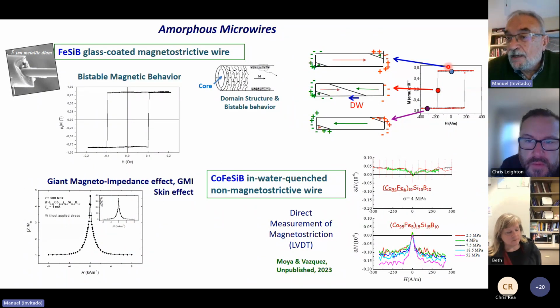So we are in a positive remanence where we have a single large magnetic domain, but at the very end where we have some magnetic charges. Then we applied a field in the opposite direction until getting a critical value when a domain wall depins from one end and moves very fast to the other end. So in the opposite stable state, we have a large domain with opposite magnetization.